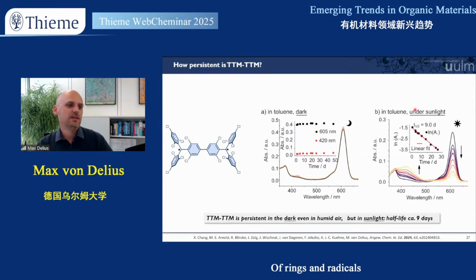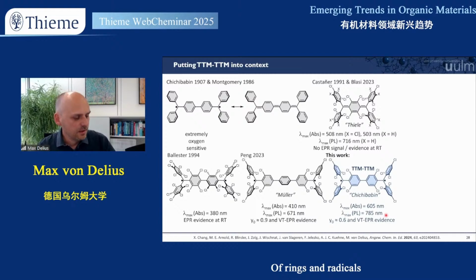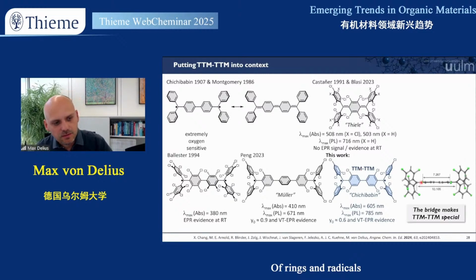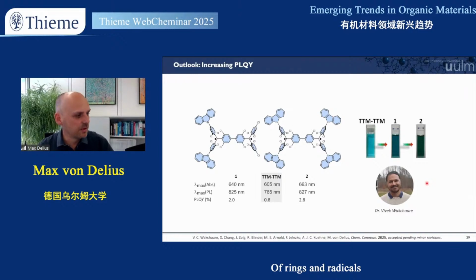If we add now bench conditions, so with some sunlight, we do see degradation over days. But the half-life is even 9 days in the presence of sunlight. So these molecules are really remarkably persistent. Now putting the result back into context, this zoo of radicals, of diradicals, the Chichibabin-type diradical that Xingmao discovered accidentally, is really unique because it has this lambda max of absorption of 600 nanometers, emission at 800, which is redshifted compared to anything else out there. And it's really having these hydrogen and chlorine atoms in just the right places. And to some extent, I would also argue the bridge is really the star of this study here, rather than really the radical.